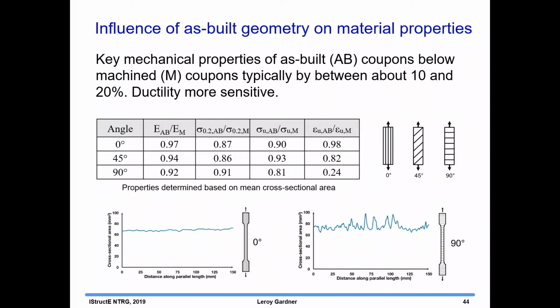So this table shows you the ratio of the key material properties in the as-built condition, so the undulating geometry, relative to the machined coupons. And you can see that generally the key mechanical properties are about 10 to 20% worse than the machined material. So that's the effect of this geometric undulation.